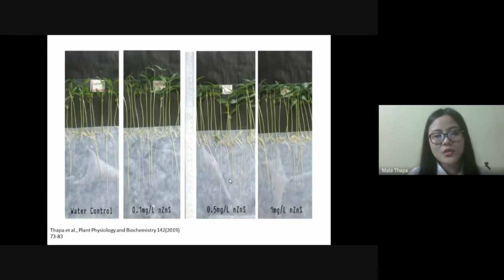This is an image of 10 days old mung bean plant treated with different concentration of zinc sulfide nanoparticle. These are hydroponically grown mung bean plants and showed that zinc sulfide treated plants were healthy and a significant increase was found in root and shoot of treated plant in comparison with the control. This result confirmed that the zinc sulfide nanoparticle has positive impact on root shoot length of mung bean plant.